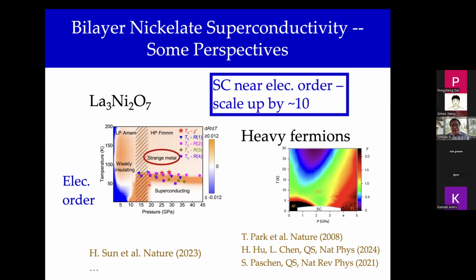So if we take a phase diagram like this seriously and look at things like strange metal labeling and the overall phase diagram, the pressure scale, the temperature scale, one could say, well, maybe it's quite sensible because this is 20 GPa. If I put phase diagrams like this for heavy fermion superconductivity, this is the phase diagram from Los Alamos, cerium rhodium indium-5 under pressure. Instead of 2 GPa, you scale up by a factor of 10, and instead of several Kelvin of TC, you scale up by a factor of 10 or so. And so maybe it's natural without thinking too much about the microscopics.